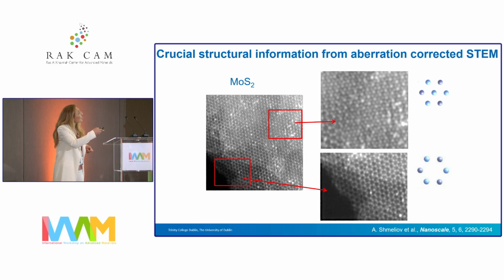So as you see, the typical honeycomb type of structure, but one of the most important take-home messages from there was that the stacking behavior is quite different. From liquid phase exfoliation, you hardly see these 2D sheets that are very uniform and very defect-free. Our 2D materials are a mess. We have loads of defects, thinner areas, thicker areas, a lot of adatoms being there because we use organic solvents, and often this is what they leave behind. And you can tell from these two zoomed-in versions, for example, the stacking is slightly shifted. So you have a lot of stacking anomalies and a very unclean type of material.